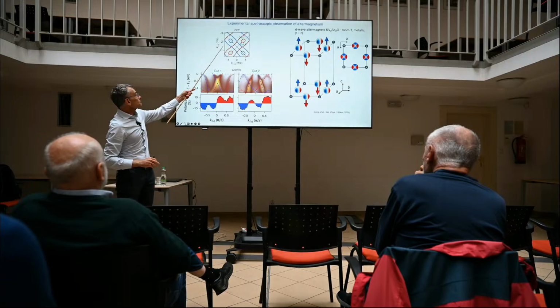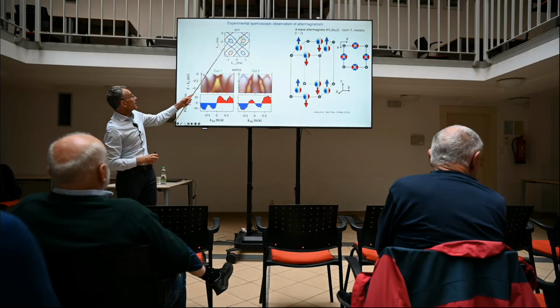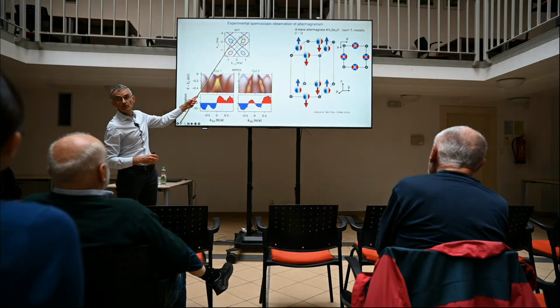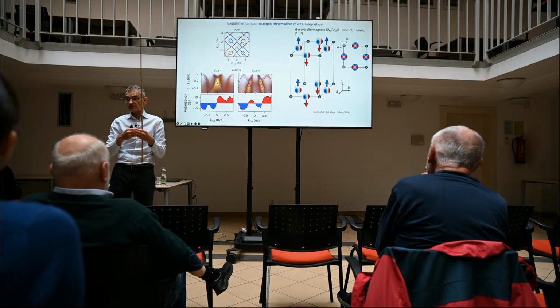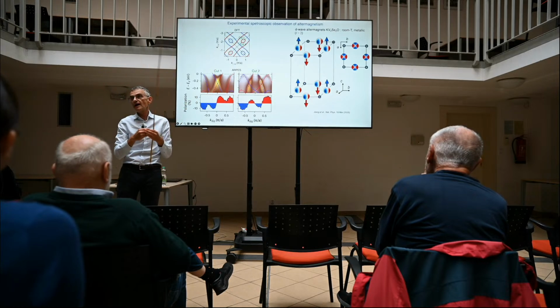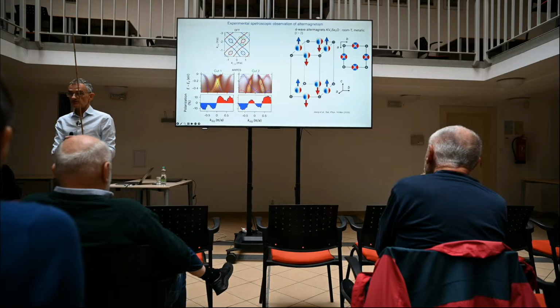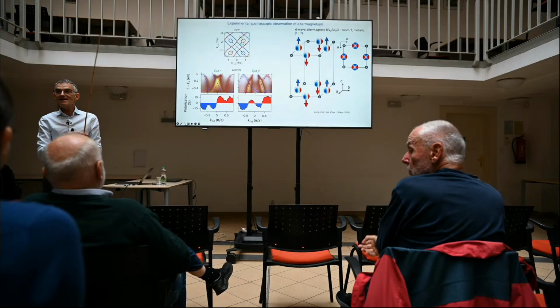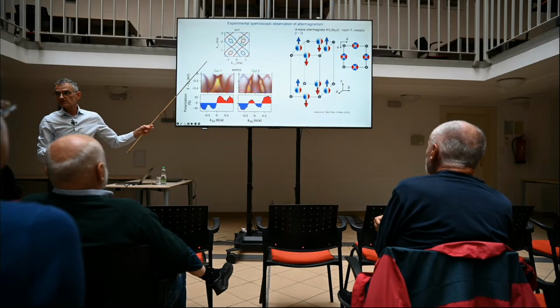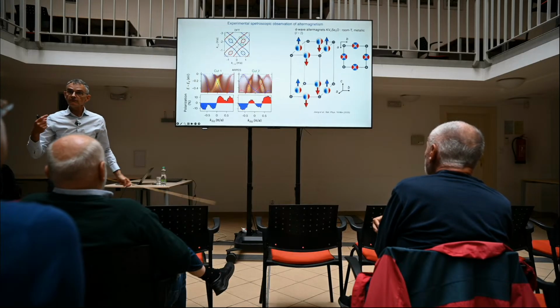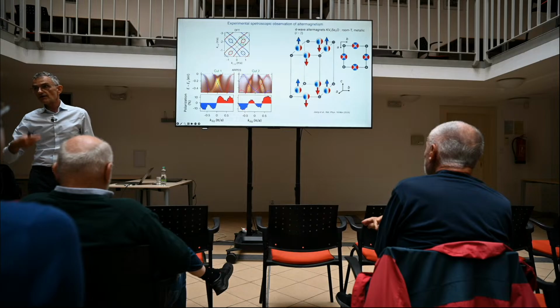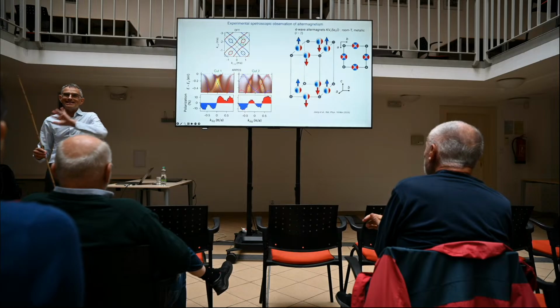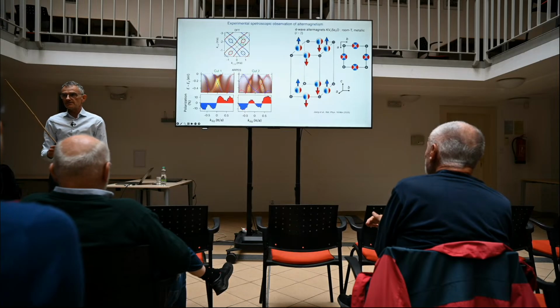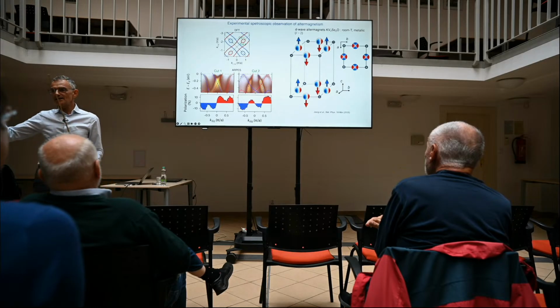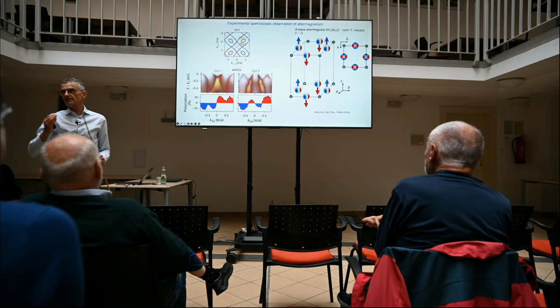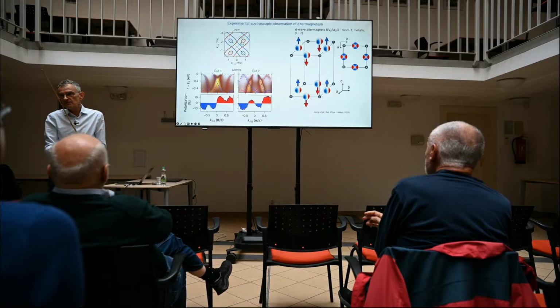Because the sign of the spin polarization alternates in altermagnets, there have to be points, there are actually planes which are spin degenerate. And they, no surprise, are the high symmetry planes or lines or points in the Brillouin zone. So there are many ARPES data on many materials which we now know are altermagnets, including, for example, the parent cuprate of high temperature superconductivity, which has been extensively studied by DFT and ARPES. And there are papers from 2019 showing all these high symmetry planes and lines which are spin degenerate, and they have to be by symmetry.